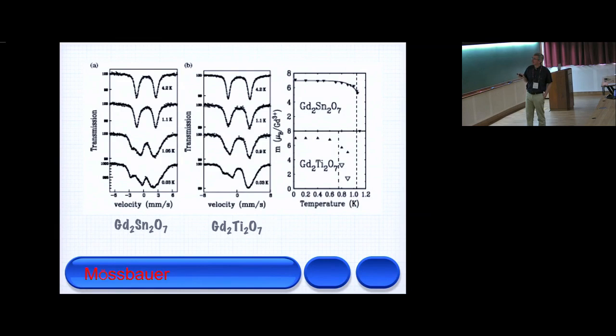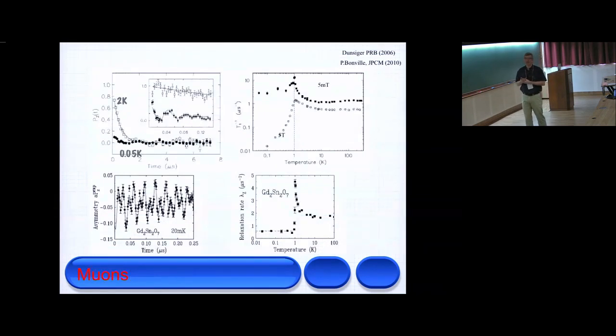Mossbauer in the titanate says that in this intermediate range, there were 2 different moments in the system. So that's what neutrons are saying with multiple Ks. In the stannate, there was only 1. But in detailed analysis of these spectra, they were never in thermal equilibrium, and they would always say there was persistent spin dynamics, these words that help you think about liquids. Muons were the same. Muons get some oscillations, but not the size that you want, or not a single frequency here. There's several beating. So they always say there's persistent spin dynamics.